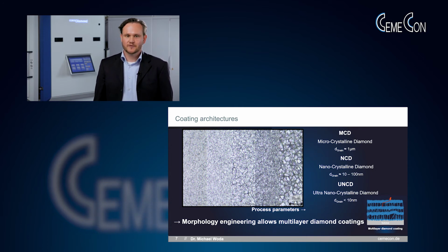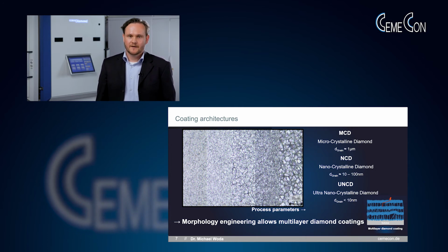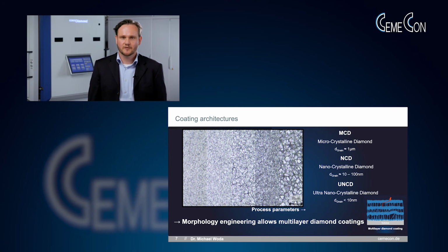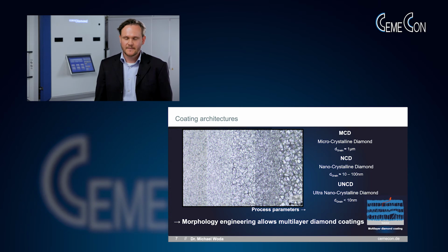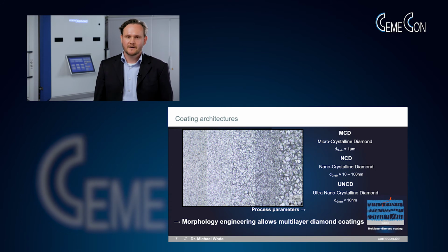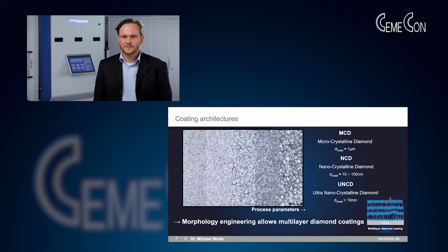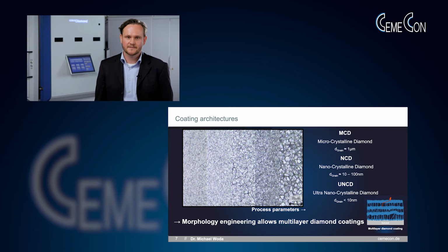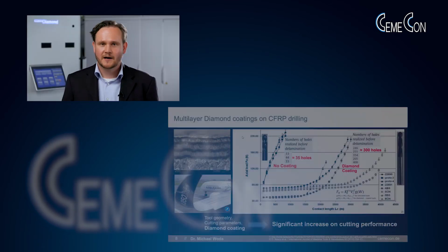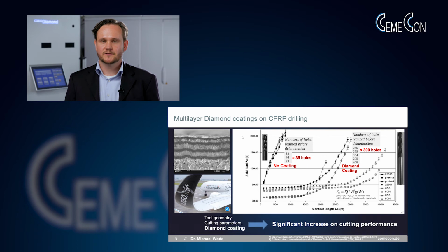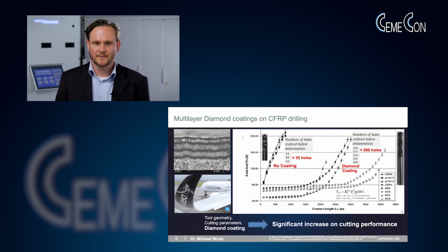Being able to do this process and to control it is only one step further to allow a very well-known and established concept in coating technology. This is coating of multilayer coatings. We are able to coat diamond multilayer coatings which show very high adhesive strength. We are able to coat very smooth top surfaces, and we have got a built-in crack resistance mechanism at the same time. We now apply these diamond coatings onto cutting tools and validate their cutting performance.